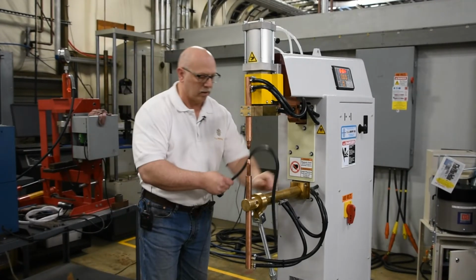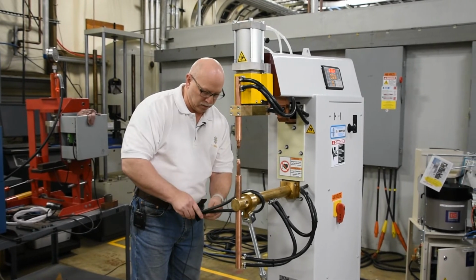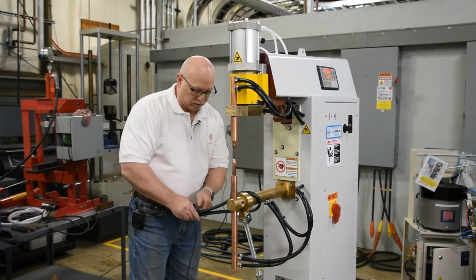With these settings in place, you'll now install the current coil from the weld current meter around the secondary copper of the machine. The weld current meter may require some basic setups such as current range, AC or DC, and the segment of the weld to be captured in the measurement. If you do not have a weld current meter and you are programming in percent, you will have to increase the current in steps of 5% until a satisfactory weld test is obtained. You will not know the output current being produced. The proof will be in the successful weld.